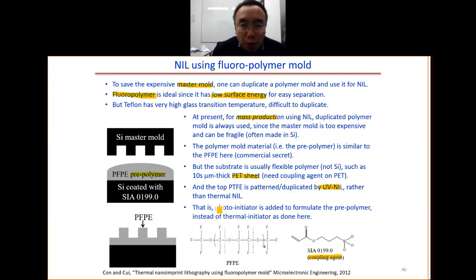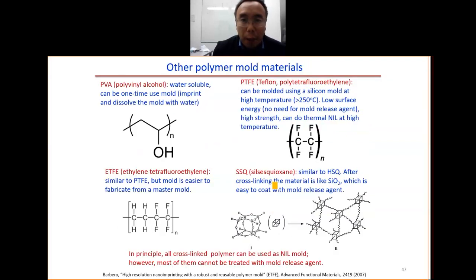That means the photoinitiator is added to this material rather than a thermal initiator. For this work here, we added the thermal initiator into this material. But for the UV imprint to copy the mold, we use the photoinitiator mixed with this material. Then you can cure the mold by UV light. So again, this is for mass production, a very, very important process.